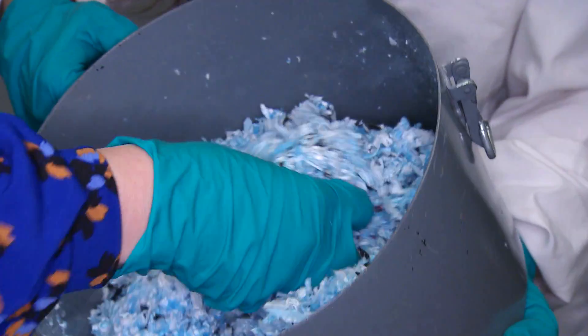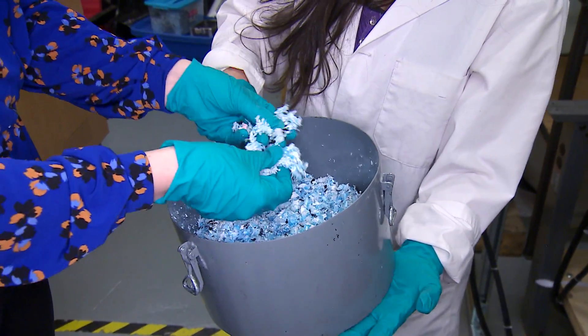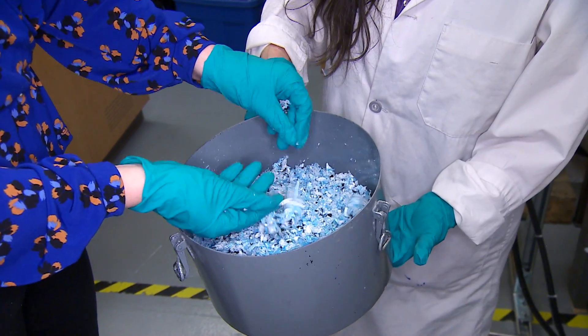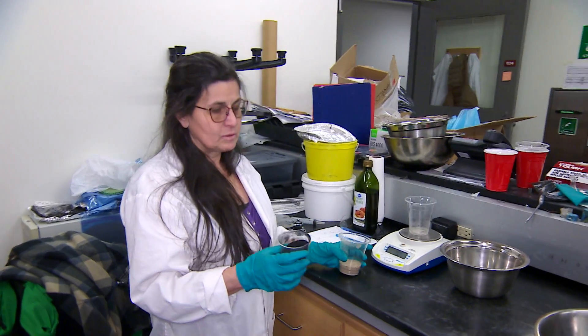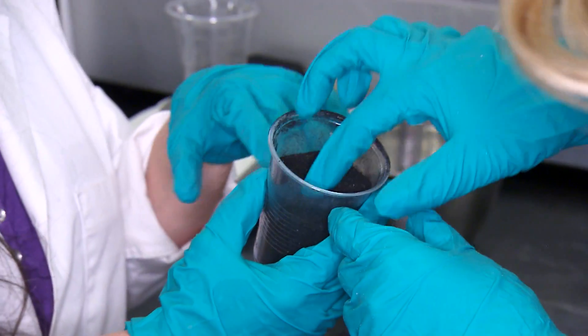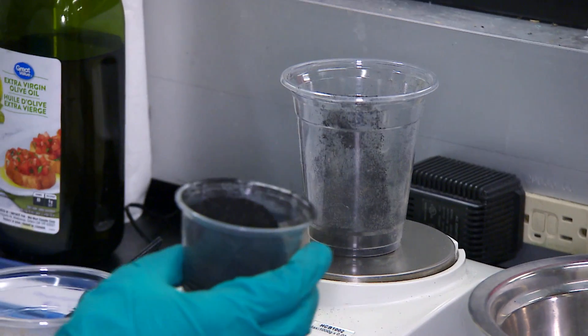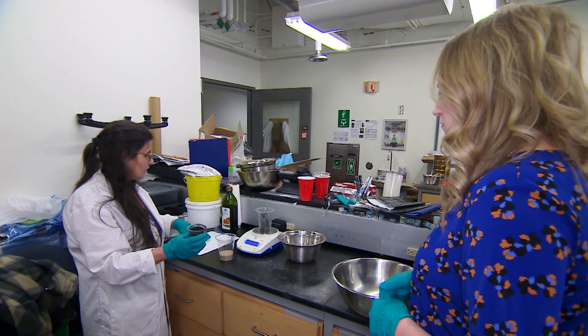The separated polypropylene will be combined with other products, first made into a sheet that gets cut down for tensile or compression specimens to assess properties, and then formed into a block or product. The recipe involves playing around with material combinations. This is crushed tire — you can see the cord in it — sourced from Shercon Industries in Saskatoon, who collect tires throughout the province and crush them down. For a 135-gram plate, 20% — that's 27 grams — will be crushed tire.